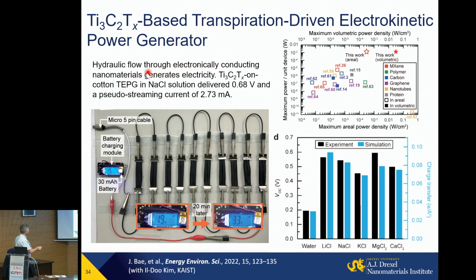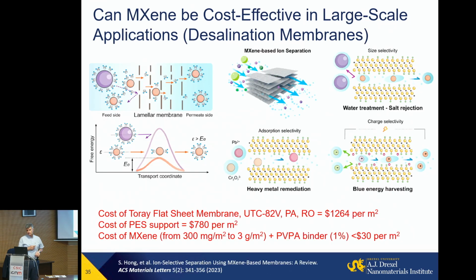MXenes, because of its high conductivity, work in a simple sodium chloride salt solution in water. You see, it's orders of magnitude higher, this is a log scale. This is basically where we stand here. So we increase by a couple of orders of magnitude compared to other materials. The performance becomes practical, capable of generating practically useful amounts of energy.